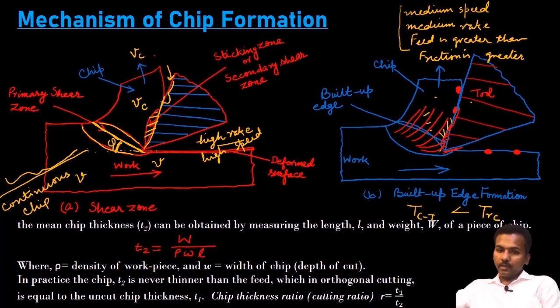If the resistance of the flowing chip material is such that it separates partially or fully some part of the built up edge, then because of the high hardness, if it comes in contact with the chip and tool, it will create lower tool life, because due to abrasion wear there will be some material decay from the tool.